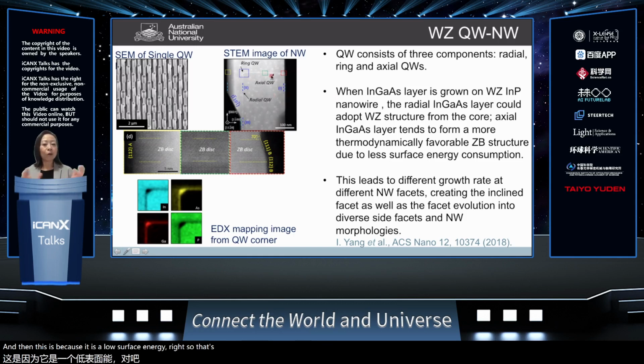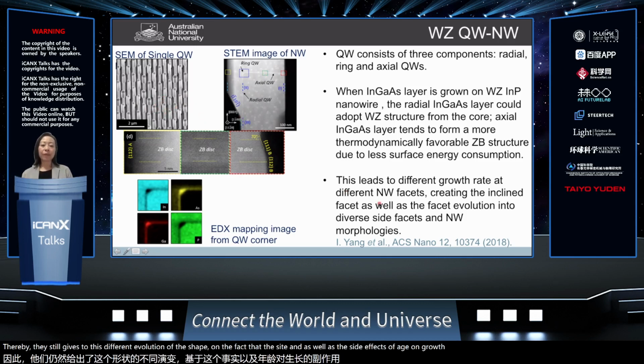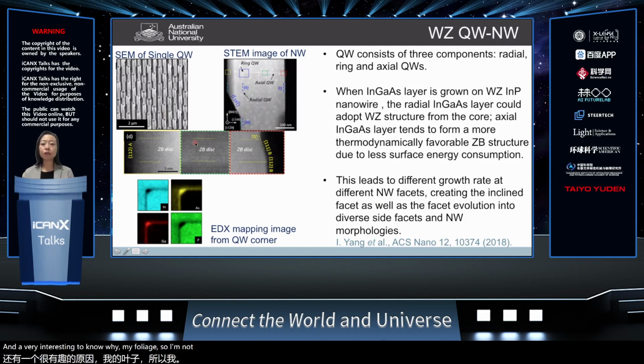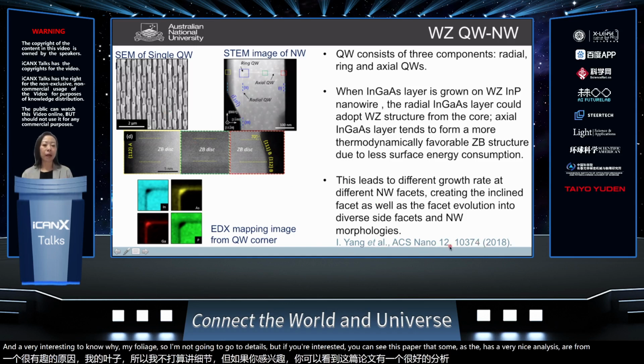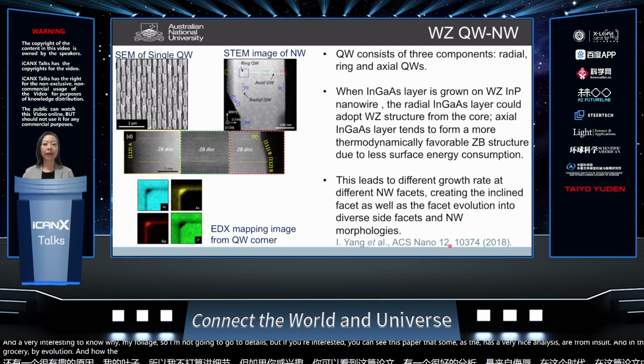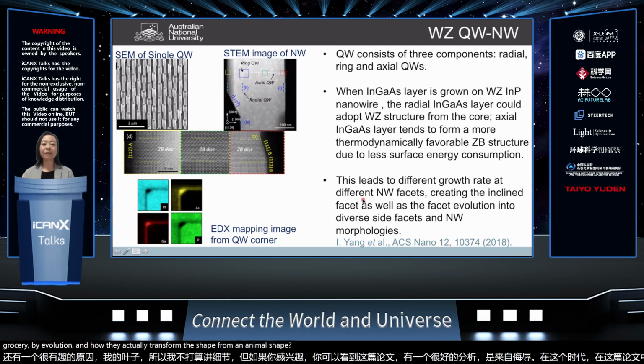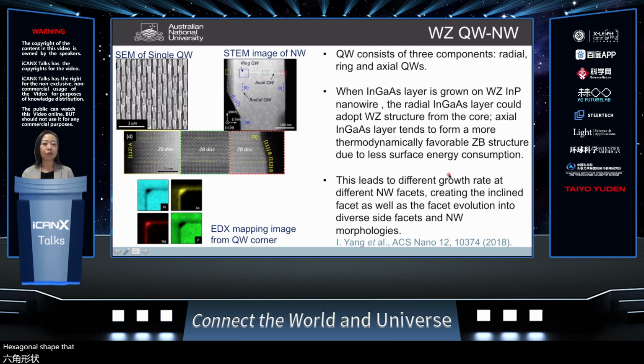Because of this different lattice formed, it leads to very different growth rates at different nanowire facets. This gives a different evolution of the shape on the side, as well as side facet growth, and a very interesting nanowire morphology. I'm not going to go into details, but if you're interested, you can see this paper that has a very nice analysis from I. Yang about the radial growth evolution, how they transform the shape from an animal shape. In the end, it can go to a very nice hexagonal shape if you grow multiple quantum wells.